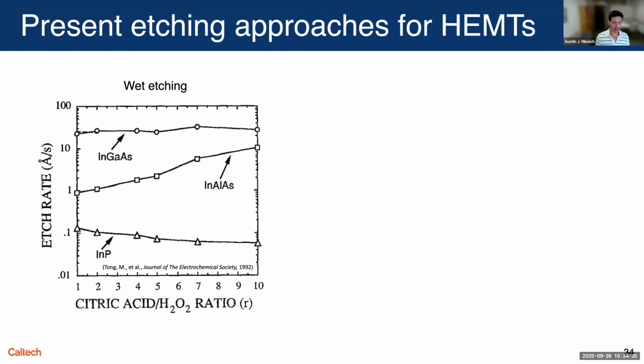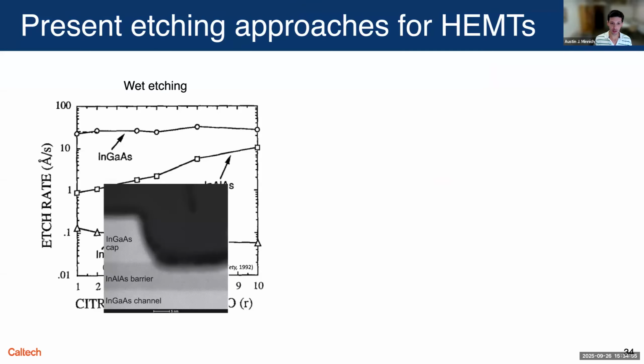So the way that this process is done now is we start with an epitaxial stack and we need to etch into the semiconductor. And over many years, there's some pretty well-known etch liquids, mixtures which selectively etch the different materials. So this is a common way that's done at present. The problem with that is that it leaves behind a pretty low quality damaged region from the wet etching. And you can see it as that fuzzy region just above the nice crystalline semiconductor in that image. And that poor quality region enhances leakage currents, and it also hosts electrical traps, which are very bad for stability.